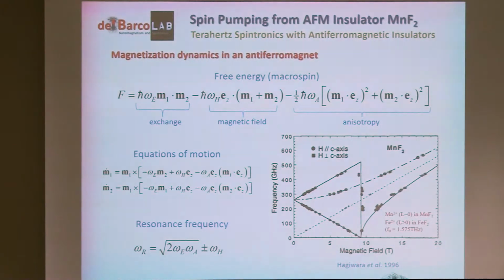All right, so the simplest view of an antiferromagnet, in my opinion, relates very much to the talks this morning, but I really like to look into this material, manganese difluoride, not just because it's the one that we have measured, but also because it's a very simple antiferromagnet in the sense that it has uniaxial anisotropy. And then you look at the free energy, and then you'll find, of course, the exchange interaction between the two sublattices, the effect of the magnetic field on each of them, and then the anisotropy, in this case uniaxial, for both sublattices, and the characteristic parameters of the three interactions, right?